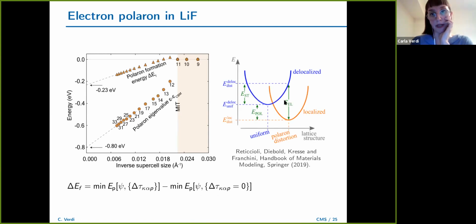This is basically described by this configuration diagram here that you can see in many, many papers. So this polaron formation energy is basically the energy that it takes to, you take an electron in a localized state, this orange line here, you promote it into a delocalized state, let's say the conduction band bottom. This vertical energy would be this polaron eigenvalue, but then the system would relax to another minimum where the atoms go back to their undistorted position. And then this energy difference would be the polaron formation energy or the polaron total energy, however you want to call it. So these are our results.